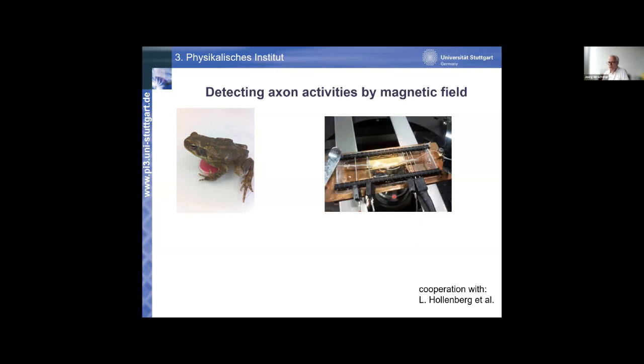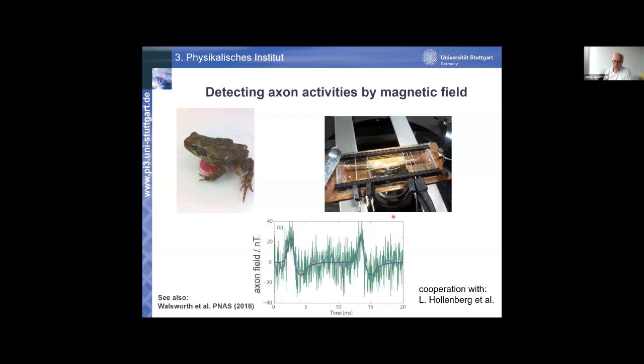Here we use the fact that with the NV center and the diamond, you can come very close to the neuron, a few micrometers distance, which is very hard for any other type of sensor, including SQUID or atom vapor magnetometry. This is why there are really very few, if any, magnetometry experiments on individual neurons before these experiments. And what you see here is the result of such an experiment.